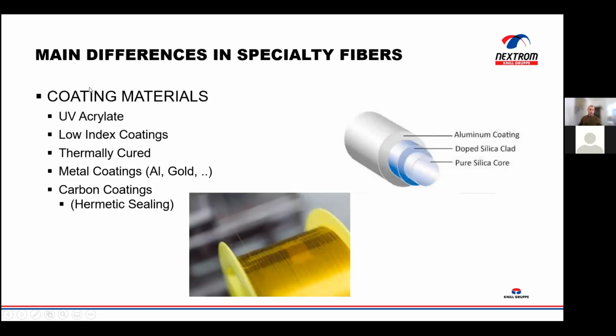And then coating materials. There's a very huge variety of different coating materials based on the need. You have a standard dual layer UV acrylate, similar to what is used in telecom fibers. Then low index coatings, hard clad, perfluorinated coatings, thermally cured, such as polyimide or silicone curings, metal coatings that can be used for hermetic sealing or radiation resistance. And within that metal, it can be aluminum, gold, silver, copper, and then carbon coatings used for hermetic sealing. So this is putting a thin layer of carbon directly on top of the fiber and then coating on top of that with something else. You can also have, as I missed here, a PTFE jacketing or some sort of extruded jacketing directly on the fiber.